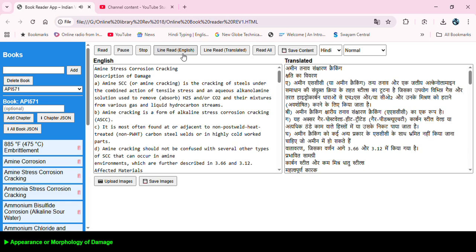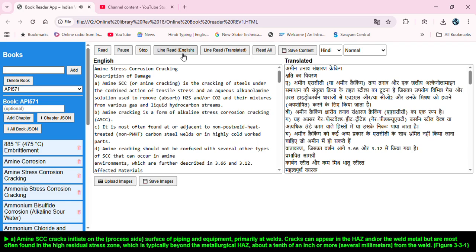Appearance or morphology of damage. A. Amine SCC cracks initiate on the process side surface of piping and equipment, primarily at welds. Cracks can appear in the HAZ and/or the weld metal but are most often found in the high residual stress zone, which is typically beyond the metallurgical HAZ, about 1/10 of an inch or more, several millimeters, from the weld. Figure 3-3-1.